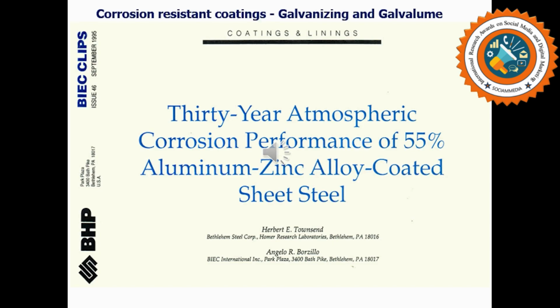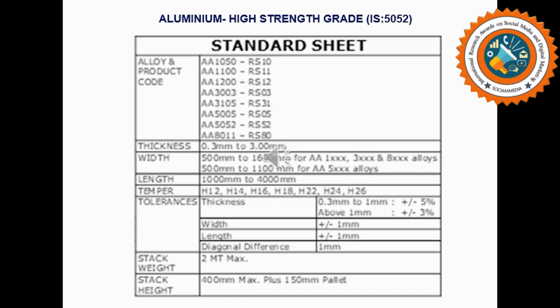To achieve better strength to weight ratio, the steel and aluminum envelopes selected are of high strength grades. The steel has Fe 310 to 550 megapascal strength, and it is of light gauge between 2 to 4 millimeter thickness, and to achieve 30-year corrosion resistance performance, it is with galvalume coating. The aluminum envelope used is of high strength grade AA5052. The thickness used is 2 to 3 millimeter.